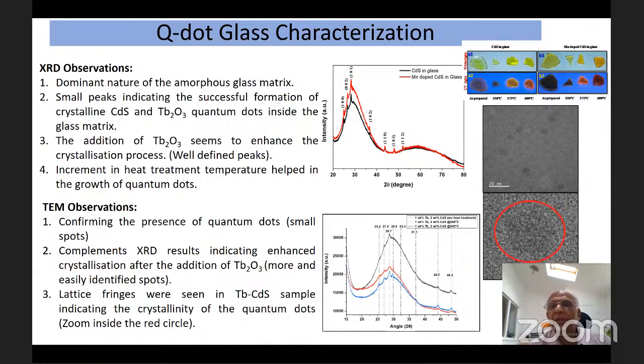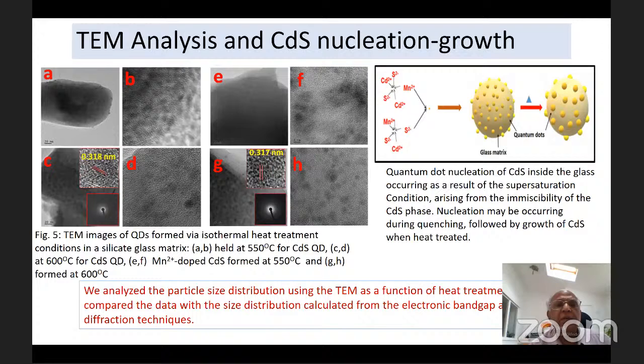And we can clearly see the lattice fringes within the quantum dots, which we analyzed also to verify the presence of CdS. In this slide, you can see how we have compared and analyzed the size distribution of quantum dots. You can see very clearly the lattice fringes.